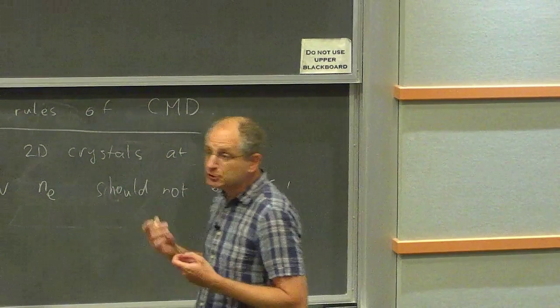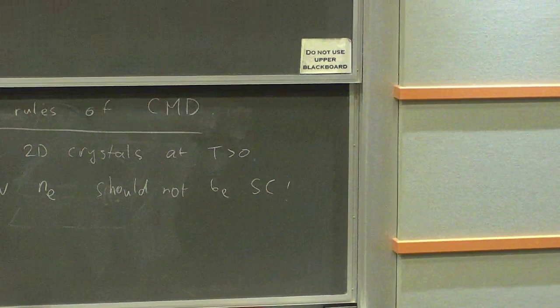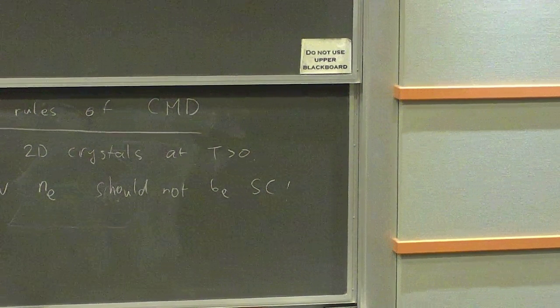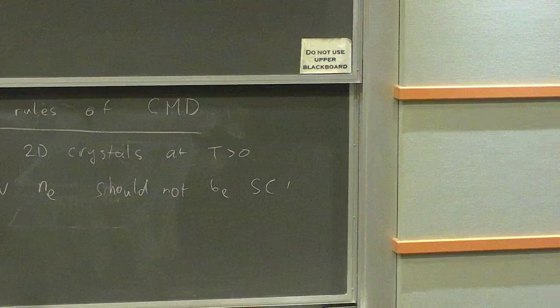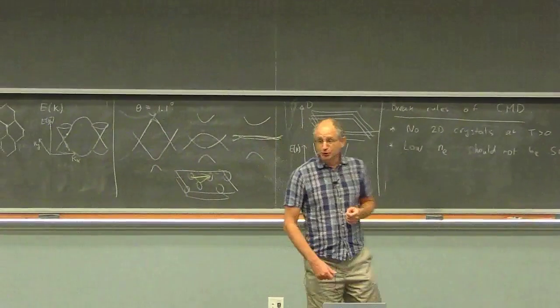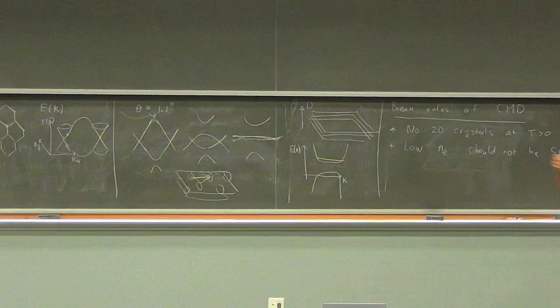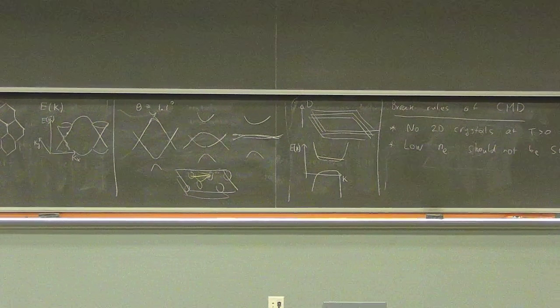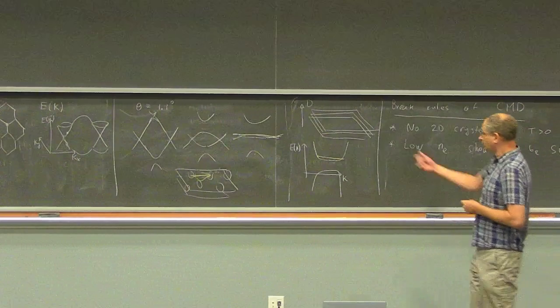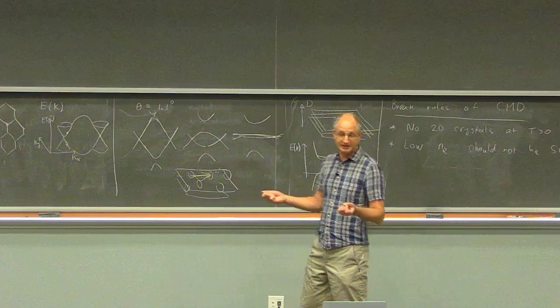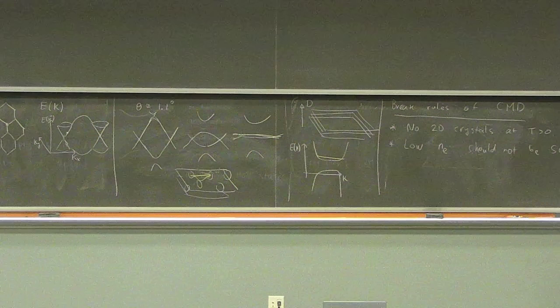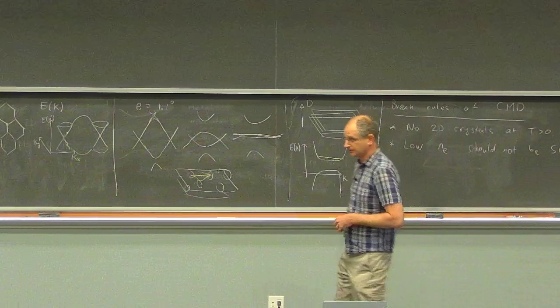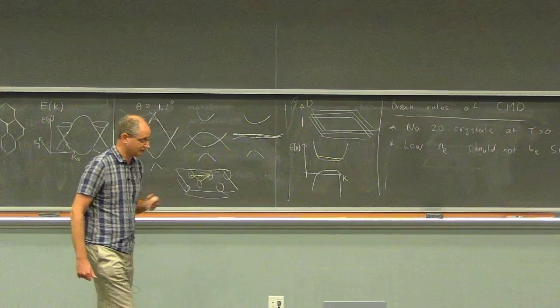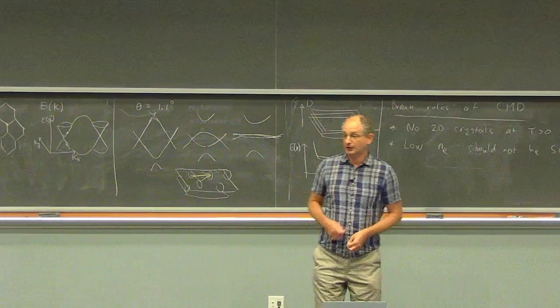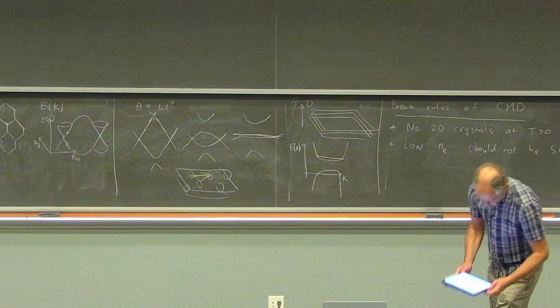The mechanism which is most well understood for how superconductivity occurs is due to interactions of the electrons with the ions, the so-called electron-phonon interaction. And for that mechanism to work, it's crucial that in an ordinary material the phonons, the lattice vibrations, move much, much more slowly than the electrons. But here we slowed down the electrons so much that the two speeds are actually comparable to each other. So all of our textbooks on how superconductivity works are basically out the window. This is, I think, one of the reasons why nobody ever thought that this would be superconducting, and we're still arguing it out. How can this happen?